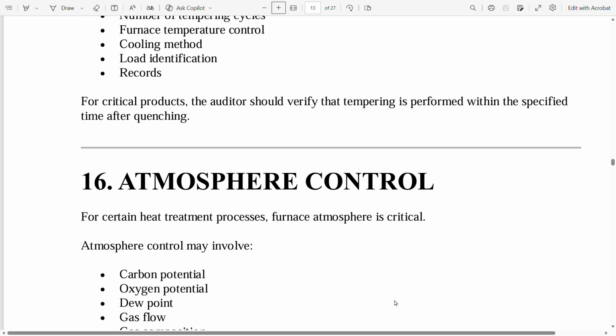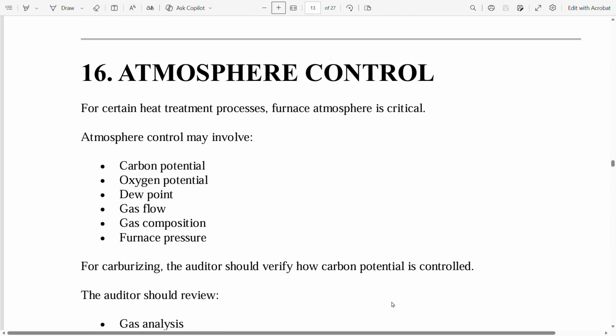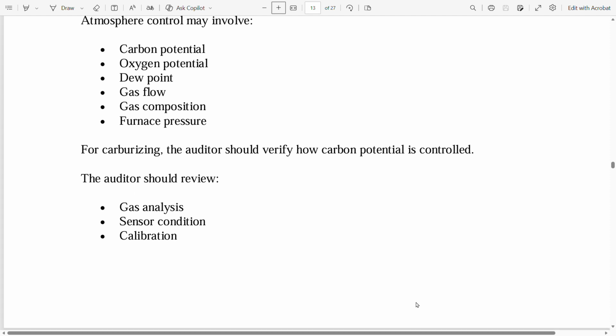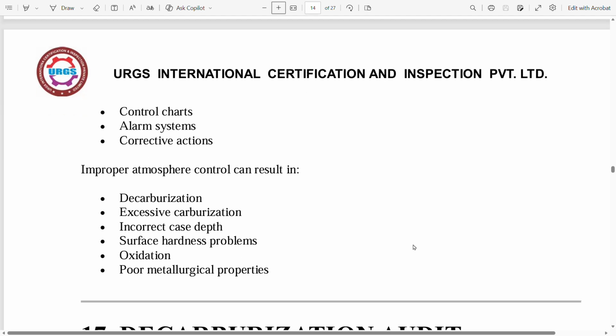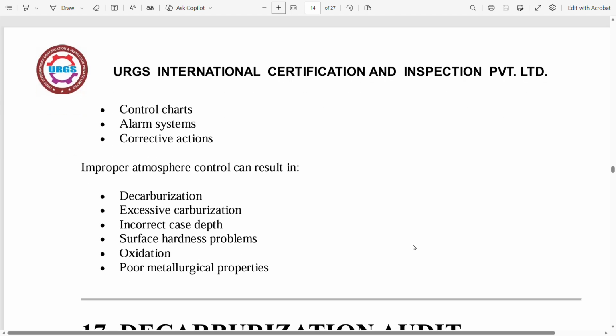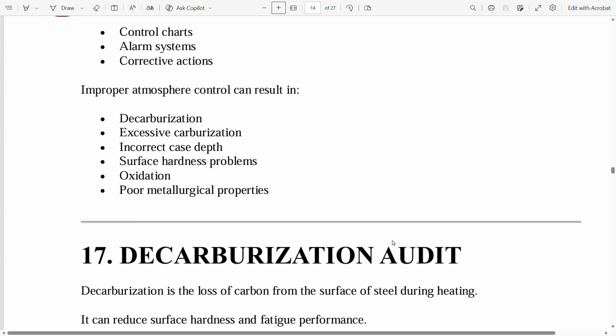The next is 16th, atmosphere control. For certain heat treatment processes, furnace atmosphere is critical. Atmosphere control may involve carbon potential, oxygen potential, dew point, gas flow, gas composition, furnace pressure. For carburizing, the auditor should verify how carbon potential is controlled. The auditor should review gas analysis, sensor condition, calibration, control charts, alarm systems, corrective actions. Improper atmosphere control can result in decarburization, excessive carburization, incorrect case depth, surface hardness problems, oxidation, poor metallurgical properties.